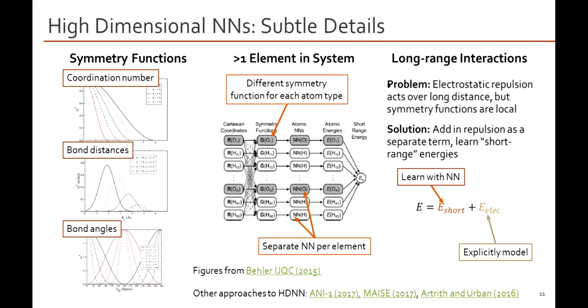I also have ones which run a filter based on bond distances, where some filters react to, say, atoms that are 3 angstroms away, where others react to those that are 4.5. So it gives me another differentiation of an atomic environment, and I also have ones that depend on bond angles. So there's that other checkbox. Angular terms are captured by having angular symmetry functions.